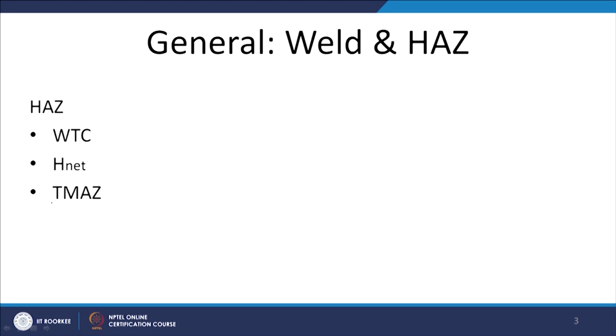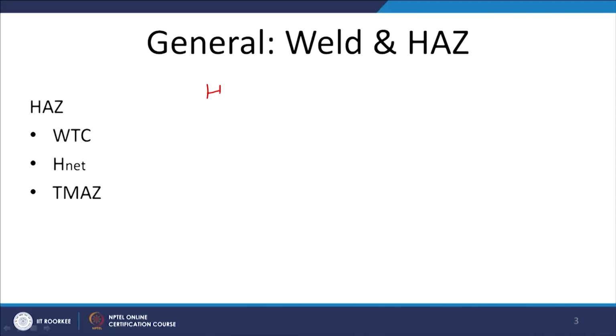As I have said, we have the option to regulate or adjust the composition as well as the weld metal properties by choosing either a matching filler metal or a completely different kind of filler metal, so that the weldability related issues of the base metal can be reduced. But we cannot do much as far as the heat affected zone development is concerned, because it is directly affected by the amount of heat being supplied for